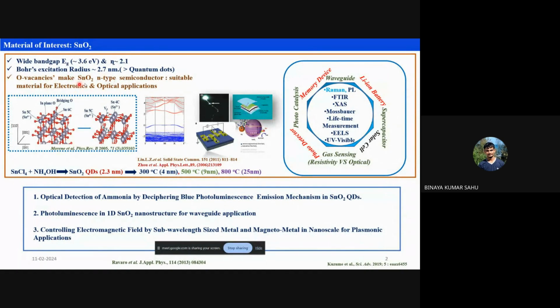And what makes this material more interesting is the presence of defects. Generally, whenever you hear the word defect, it gives a negative impression, that defect is not good. But for a material like tin oxide, defect is very good. As I explained, this is a wide bandgap material, and here you can see these two levels, which don't present in general, and the difference from here to here is the actual bandgap of the tin oxide.